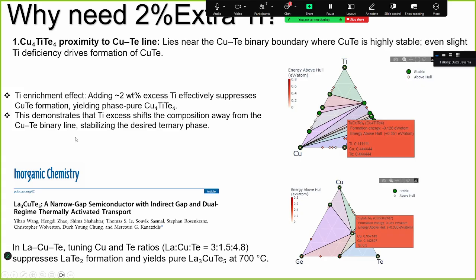My assumption is that it's near the copper telluride binary line. So without titanium, maybe in ball milling some titanium is deficient or something is happening, so that's why the copper telluride is stable, and excess titanium can react with that copper telluride.